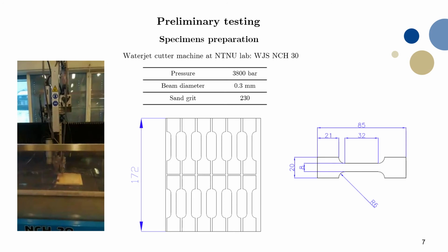Due to the low strength, special care has been given to the specimen preparation. The specimens were cut by means of a water jet cutter machine at the NTNU lab, and here is the geometry of the specimen, which is very small with a cross section of 16 square millimeters.